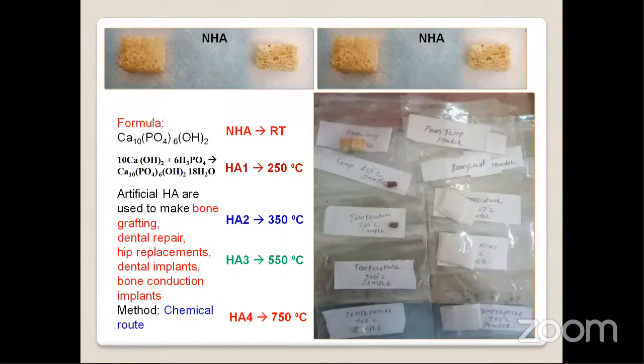Why? Because it is a very tedious process to get ethical authentication from the government to discuss all these bone studies. Here, this sample one can see at room temperature, at 250 degrees centigrade, 350, 550, and 750 degrees centigrade. One could see the different colors in the sample. First it is yellow, then brown, then again brown, and some whitish, that is ash white, and then here the pure white. Once you reach this pure white, after that it becomes ash. When you are reaching a temperature of nearly 800 to 850 or 900, it is completely ash.